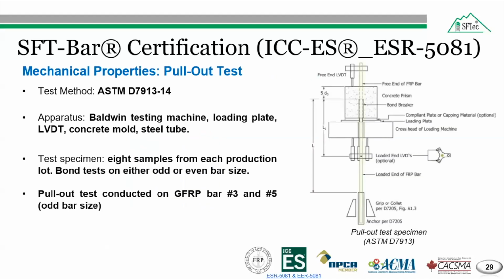So coming to the last mechanical property test, which is the pull-out test, it was performed to measure the bond strength between the reinforcing bar and the concrete. The test apparatus consists of a bond testing machine, loading plate, LVDTs at fixed and free end to measure the displacement, concrete mold, and steel tube. So here ASTM D7913-14 allows bond test on either odd or even bar size designation if a range of identically produced bar is offered. Therefore, the pull-out test was conducted on GFRP bar number 3 and 5, which are the odd bar sizes.